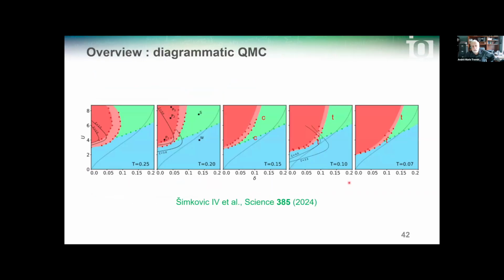That brings me to this recent work of the Paris group obtained with diagrammatic quantum Monte Carlo. These are interaction-temperature phase diagrams obtained at 5 different temperatures, 1, 2, 3, 4, 5. In red is the pseudogap region. In green, a strongly correlated metal. And in blue, a Fermi liquid. The solid line is the zero temperature phase boundary between the spin density wave or stripe phase and the Fermi liquid. The extrapolation to zero temperature of the phase diagram suggests that the pseudogap ends at this boundary and that the pseudogap is a precursor of that phase.